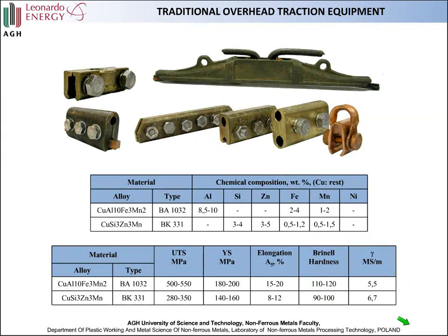All types of equipment are made from different bronzes, and they have relatively good mechanical properties and high corrosion resistance, but they have a very low electrical conductivity. Equipment made of these materials has a number of defects in shape, surface, and internal defects arising from the casting process and the production technology, and also this requires large size of equipment to ensure the strength of the material. It poses the risk of degradation of mechanical properties of the conductive and carrying elements of the line.